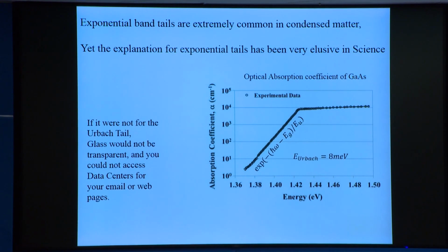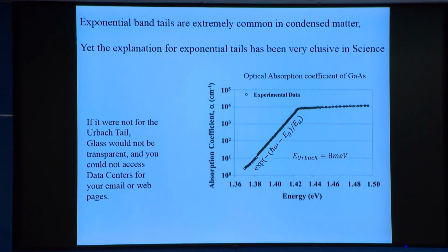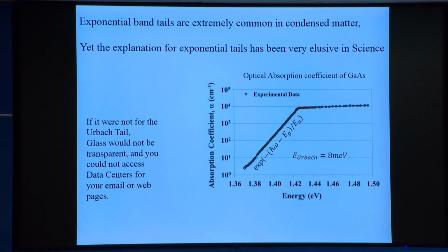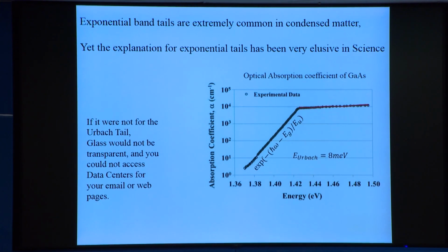They're very common in condensed matter. For example, every semiconductor, in fact almost every transparent material, if you look at the conduction band edge, for example gallium arsenide, where there's a lot of good data. The absorption of the gallium arsenide is minding its own business, and where there should have been a step function because you reached the band edge, there's never a step function.